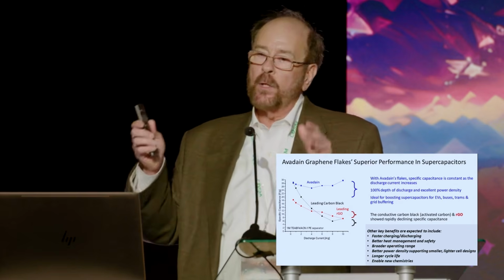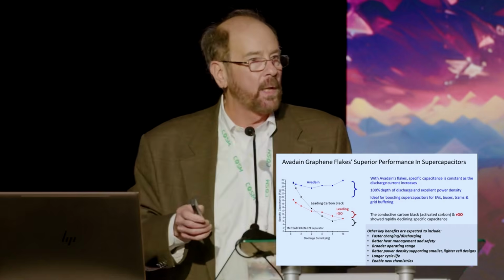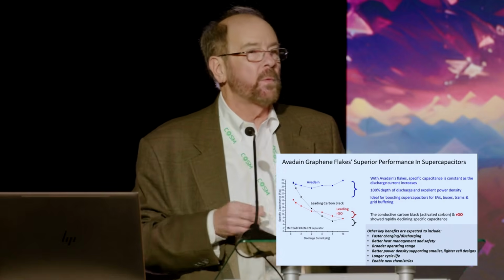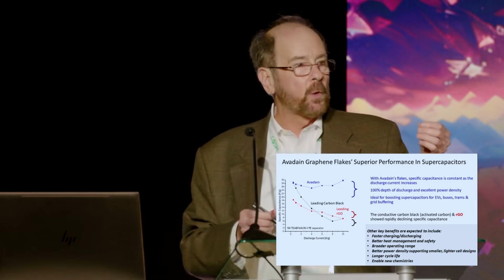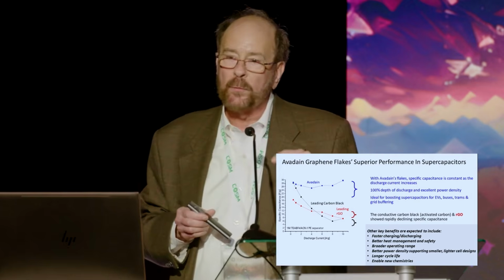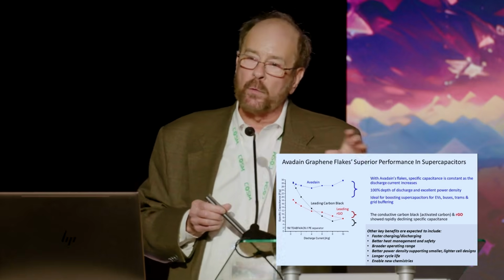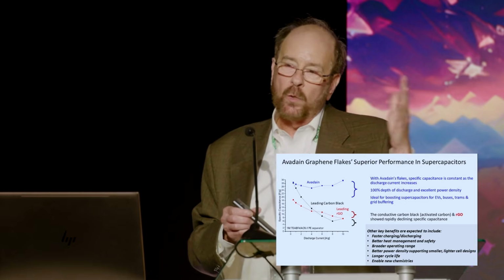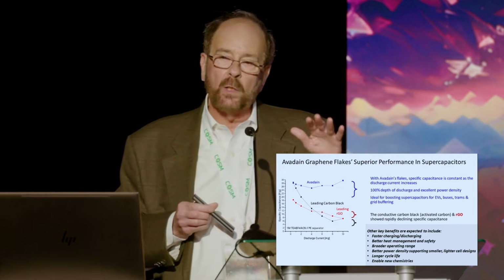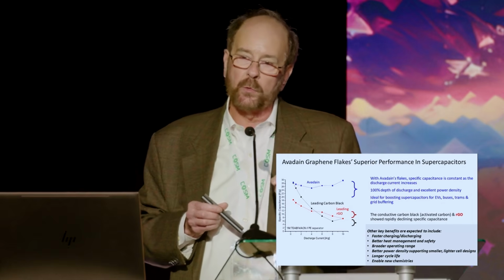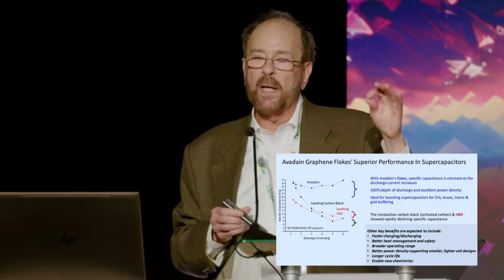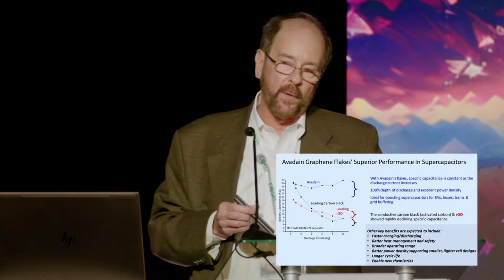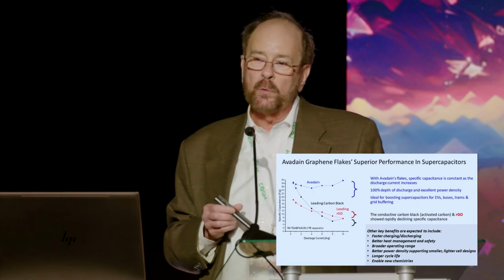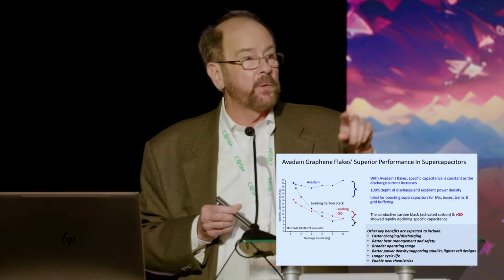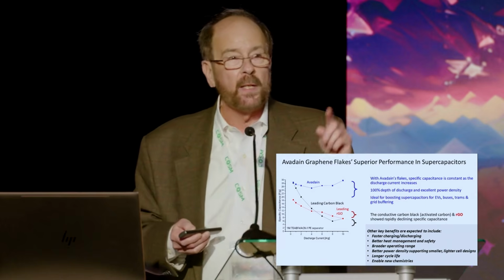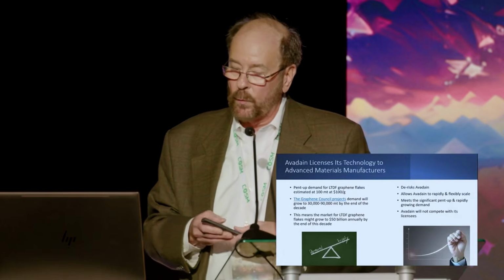Why is that important? Because as we move to electric vehicles that need to be rapidly charged, high-quality graphene can do that. We believe that we will see a transition from spherical graphite in electric vehicle batteries to using graphene. About 20 to 30% of the weight of an electric vehicle battery is the anode material, which uses spherical graphite. That can largely be replaced by 3 atomic layers of graphene. So not only will we reduce the graphite used, which will result in a cost savings, and wean us from the supply chain issue, because China produces most of the spherical graphite used in our electric vehicle batteries, but we can decrease the charging time to minutes instead of hours because of the high electrical conductivity of graphene, and without producing heat, which currently is a huge problem for anode materials.